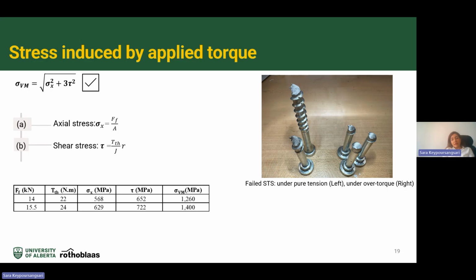So in this part, we focus on finding the stress on self-tapping screws. As I mentioned, we did a tension test, and you can see the results here. These screws failed under pure tension, and these screws failed under pure torsion. You can see that the failure in these two is different. So this is why we thought that, when we are over-torquing our self-tapping screws, the effect of the shear stress is something important.